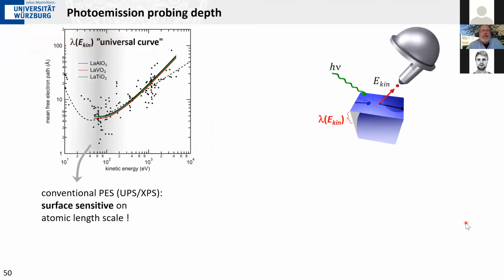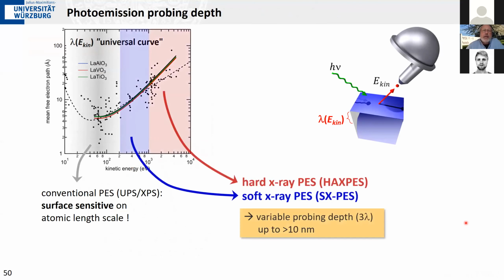Now, the way out is to go away from these small mean free paths by going to higher and higher photon energies. As we go to the right here in this universal curve, you see that the mean free path is increasing as we go to higher energies, but higher photoelectron energies means I need higher photon energy to get them to this high kinetic energy.